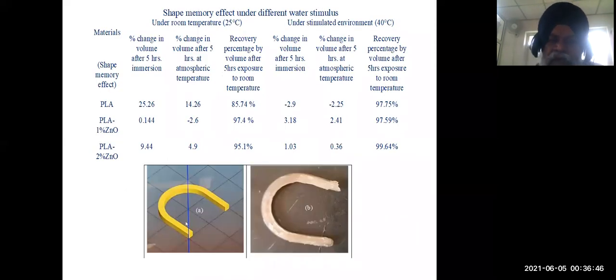Then basically, we print a component like a U and we put it into the water at room temperature of 25 degrees Celsius, right? And then we remove that part after dipping it, let us say for 5 hours, and what we observe, this U becomes V, right? So there is a change in the outer edges, suppose it is a fork-type thing, so there is a change in the dimension. But once we put it for some time, again it has shown some recovery. Then we try to see the same effect at some different temperature, let us say 40 degrees Celsius. You can see the recovery was more, around 99% recovery we are getting.